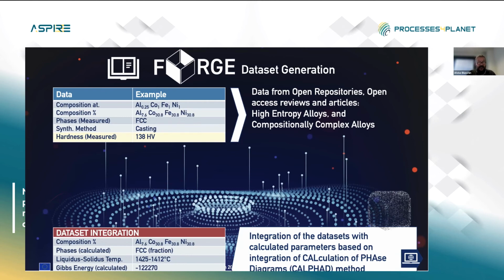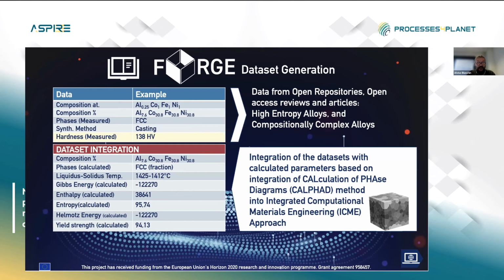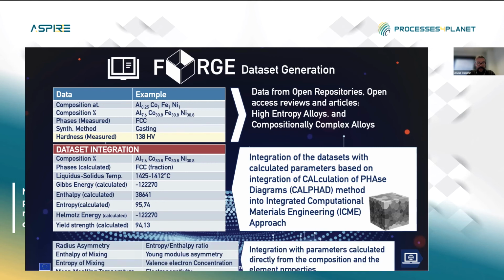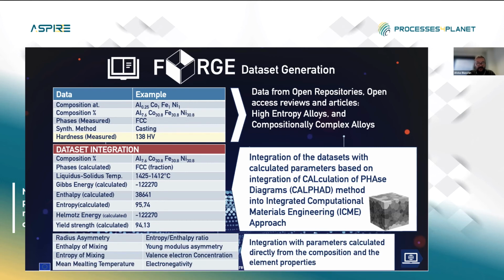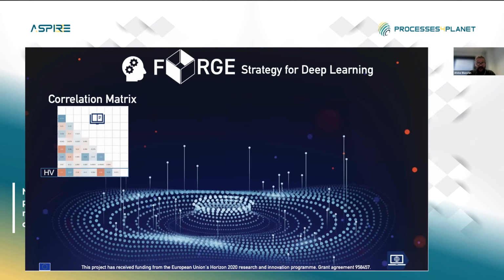These data have been integrated with data coming from physical modeling methods in order to provide the data set with more complete information on the specific composition, and also integration with other parameters calculated directly from the composition. So we had to use CALPHAD connected with Python systems in order to provide a huge data set of information of this type. This information has been used to obtain a correlation matrix that is able to identify which information is more related to, in this case, the hardness value.